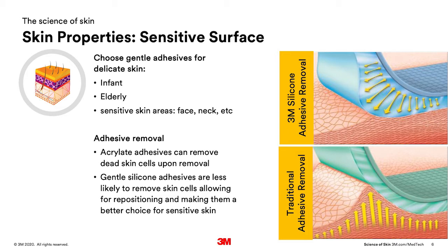An alternative option in these cases is to use a silicone adhesive. Silicone adhesives will remove fewer skin cells, are less painful to remove, making them ideal candidates for sensitive skin applications or in use with a device which will be removed and reapplied multiple times.